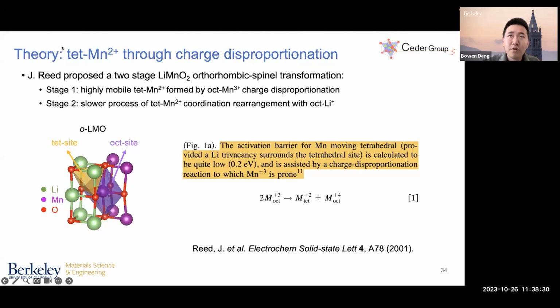So John Reed, actually an alumnus of the Ceder Group, proposed this two-stage lithium manganese oxide orthorhombic to spinel phase transformation. In his proposal, this phase transformation happens in two stages. In the first stage, highly mobile tetrahedral manganese 2+ ions are formed by octahedral manganese 3+ ions through charge disproportionation. The second stage is the slower process of this tetrahedral manganese 2+ coordination rearrangement with the octahedral lithium ions. If you write this as a simple chemical reaction, two octahedral manganese 3+ ions transform into one tetrahedral manganese 2+ and one octahedral manganese 4+.